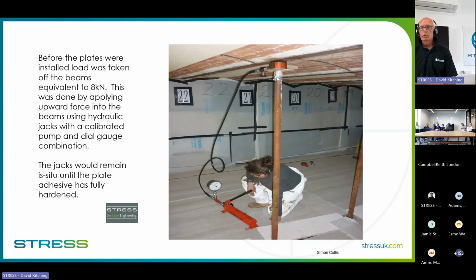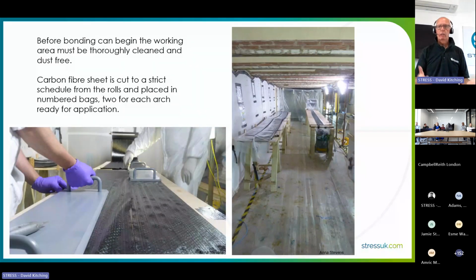What we also did was jack a little bit of load out of the beams. Now they're not flexible like steel beams, so we've got to be very careful, and we actually put 8 kilonewtons of load into each of those props and maintained that throughout the installation of the carbon fiber. That's Annie. She is our conservation manager, and got involved in the project to make sure that everything went according to plan. That obviously just relieved a bit of load and lifted the balcony very slightly, which helps when you put the load back in. Carbon fiber sheet, lovely working environment.